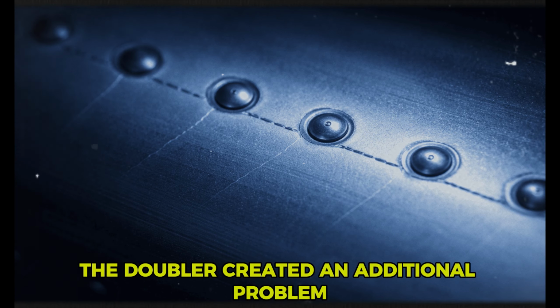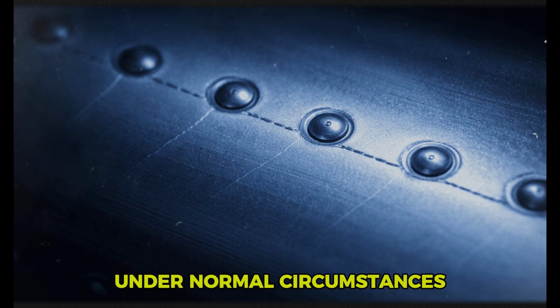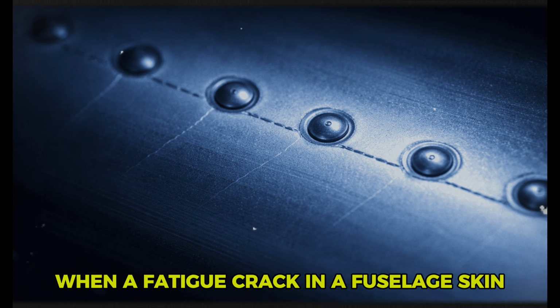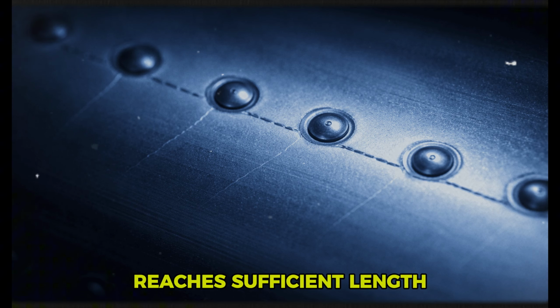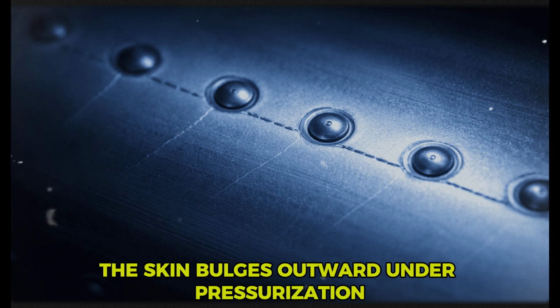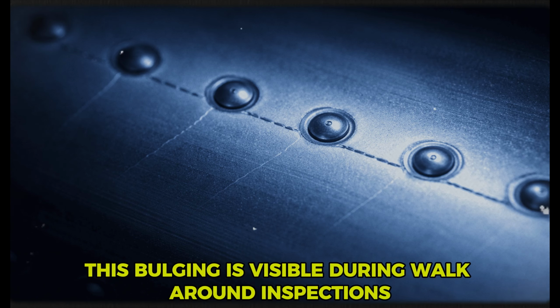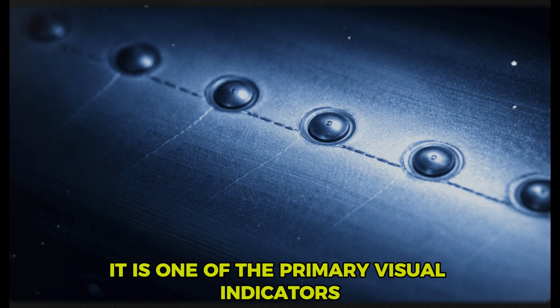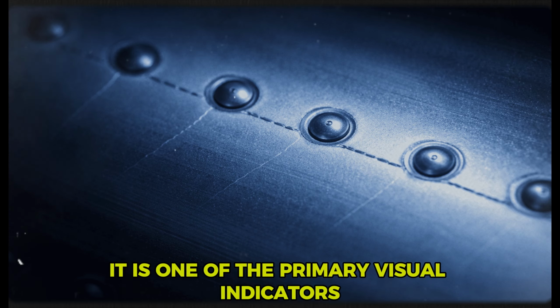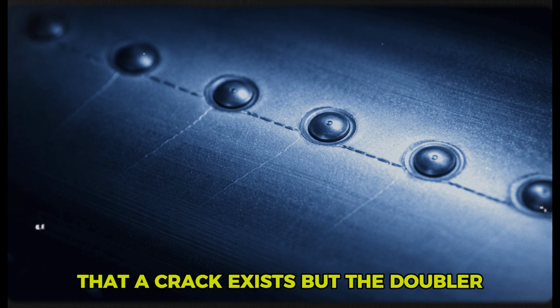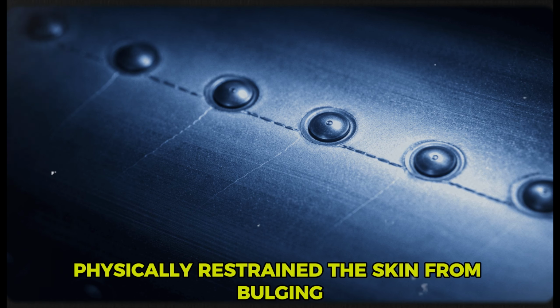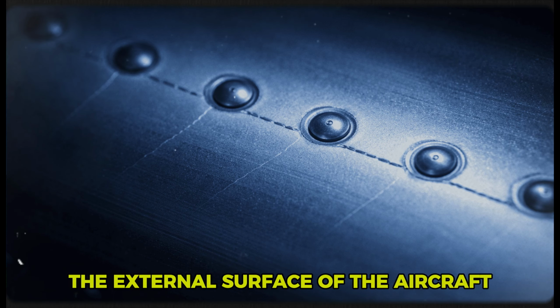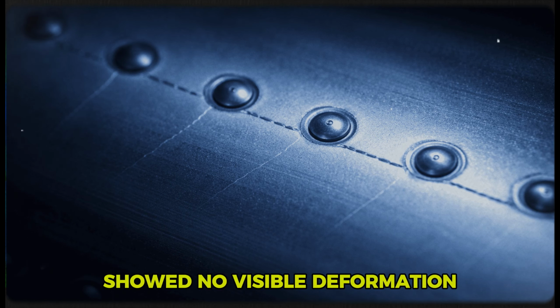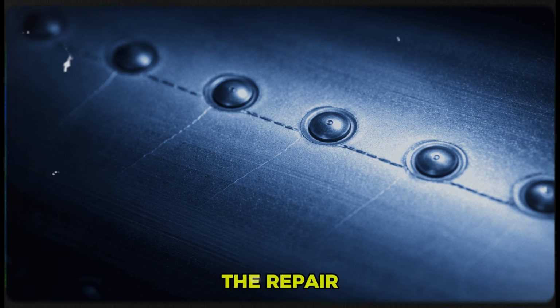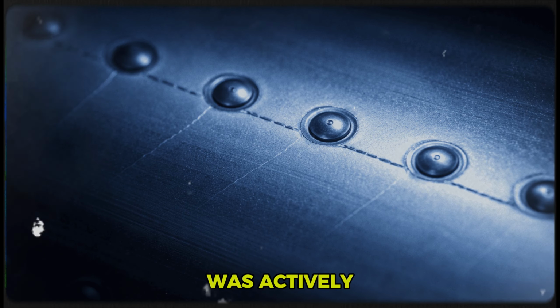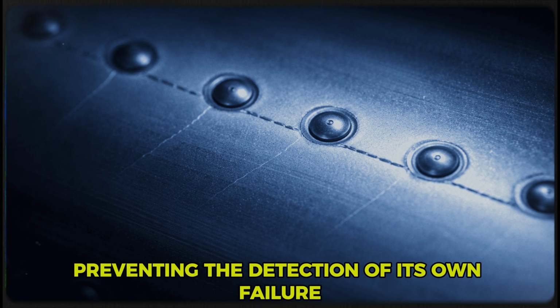The doubler created an additional problem. Under normal circumstances, when a fatigue crack in a fuselage skin reaches sufficient length, the skin bulges outward under pressurization. This bulging is visible during walk-around inspections. It is one of the primary visual indicators that a crack exists, but the doubler physically restrained the skin from bulging. The damage remained flat. The external surface of the aircraft showed no visible deformation. The repair that was supposed to strengthen the structure was actively preventing the detection of its own failure.